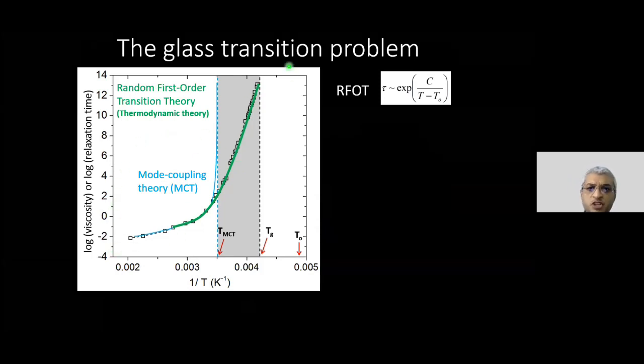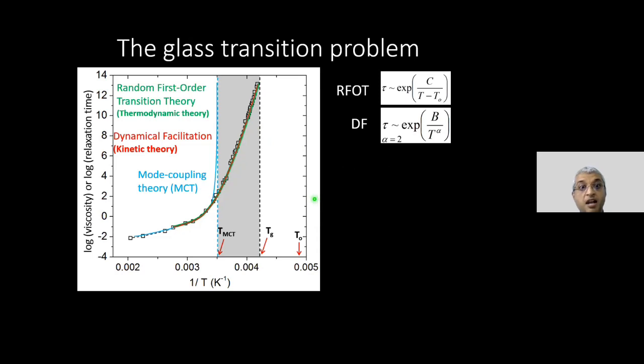So we know there is a theory called the mode coupling theory, which doesn't describe the slowing down. It starts deviating from the relaxation time data quite early on, okay? Now, there are these two other approaches. One is called the random first order transition theory, which basically says the relaxation time diverges at a finite temperature T naught. That fits the data beautifully well. There's also this theory called the dynamical facilitation theory, which says the relaxation time diverges only at T equal to 0. So this is a purely kinetic theory, this is a purely thermodynamic theory. Both of these lines fit the experimental data equally well, okay?